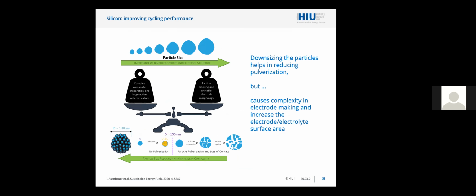So it has been demonstrated that if you go very small in the particle size, then you can have the lithiation without pulverization, which is okay. But this is obviously introducing a very complex composite electrode preparation. You have a very large active material surface area, and this may then require a huge amount of charge for the formation of the SEI.